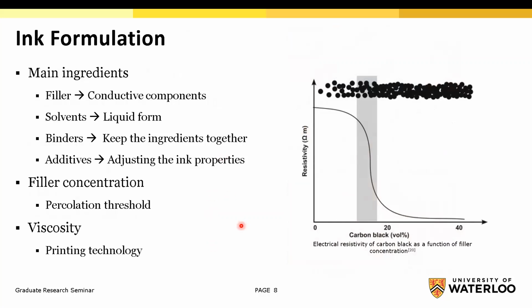For an ink formulation, there are four main ingredients: fillers, solvents, binders, and additives. Fillers are the conductive components, which make the ink conductive. You need solvents to give the ink a liquid form. Usually alcohol or other solvents can be used. Binders keep the ingredients together. And additives are for adjusting the ink properties, like thickening agents for adjusting viscosity, defoamers to prevent foam generation, and leveling agents to provide good leveling for the ink.